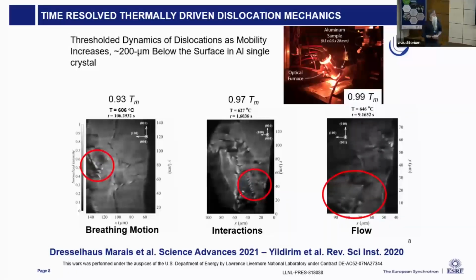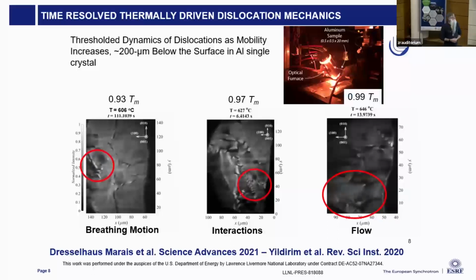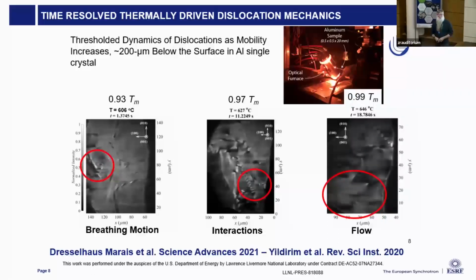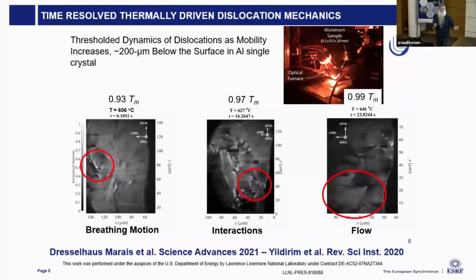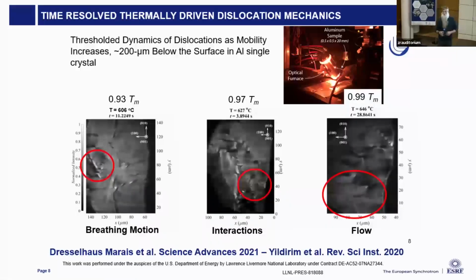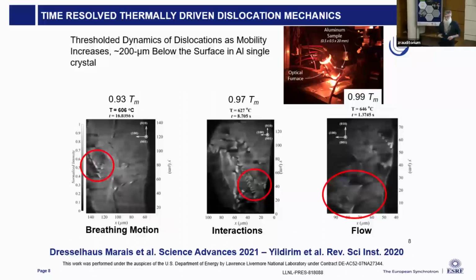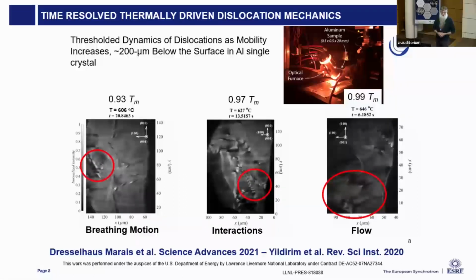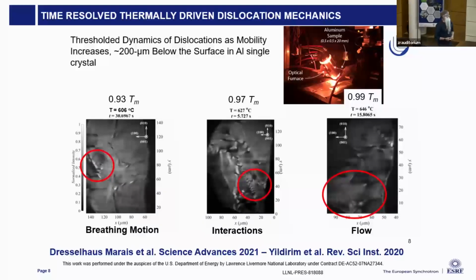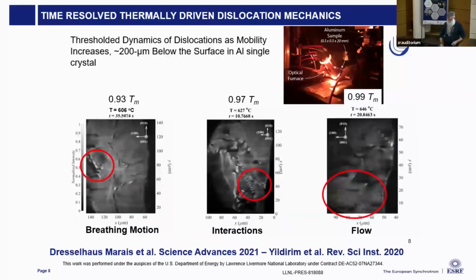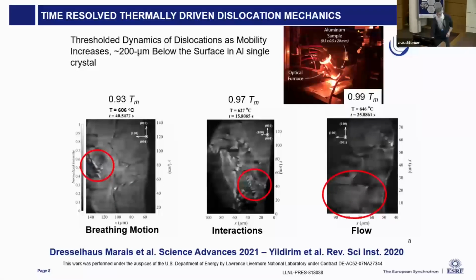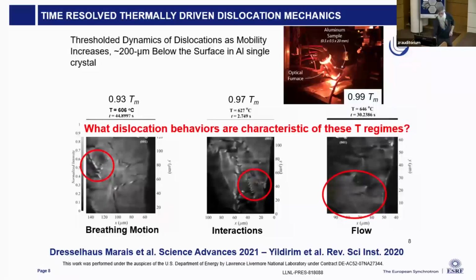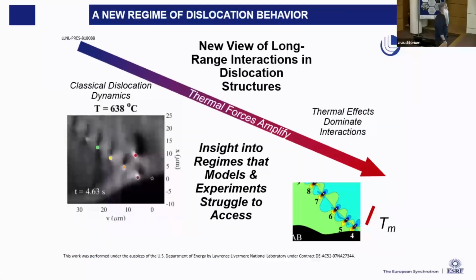And the expectation was to some extent that close to the melting temperature, it shouldn't really matter how far away from the melting you are, the behavior should be roughly the same. But what we found in our experiments is that is not the case. And there's not only quantitatively, but qualitatively different behavior of these dislocations so close to the melting temperature. So that is food for theory, of course.